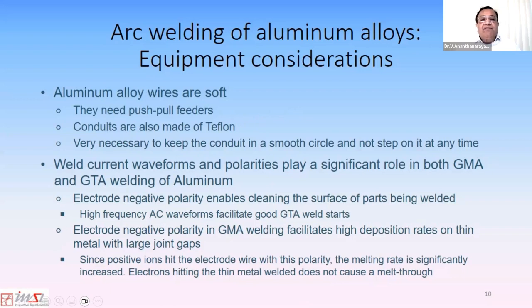Secondly, the welding current waveforms and polarities play a significant role in both gas metal arc welding and gas tungsten arc welding of aluminum. And as you all know, aluminum has a very high affinity for oxygen. If you, for instance, use some emery paper and clean the weld area free of oxides, and then you take a break and go to lunch and come back, the oxide has already formed on the surface you just cleaned prior to the lunch break.